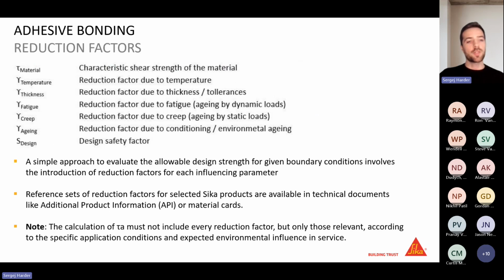Another part where we often get questions: now I see this characteristic shear strength for my adhesive. Can I just use this strength for my design? And oftentimes it also depends on what temperature you will see in your application, and you will have to consider the reduction factors for that. So for example, most adhesives will lose some strength at higher temperatures, but also gain some strength if you have lower temperatures than room temperature. And this you will need to consider with these reduction factors. Also, thickness tolerances can play a role, and also fatigue loads and so on. And also considering the safety aspect of your application, you will maybe need to introduce some design safety factor.